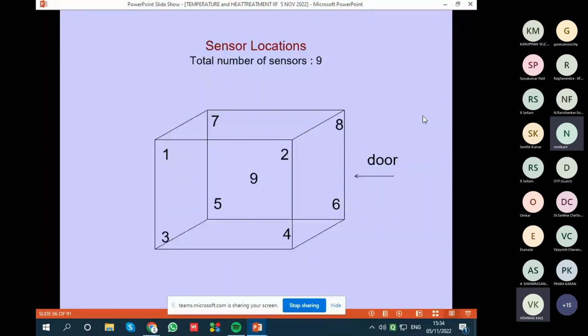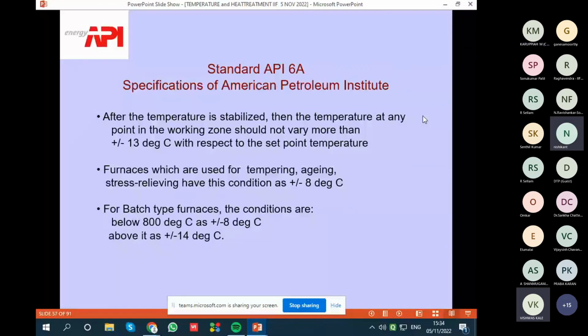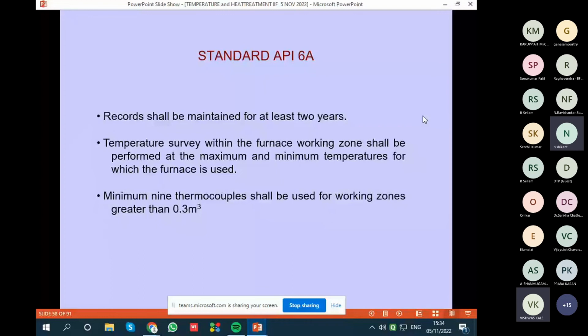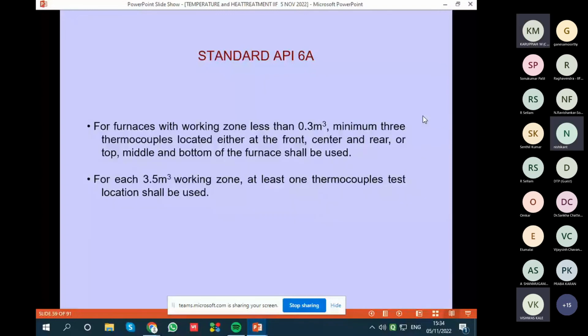Then I'm taking a typical example. The standard set by API 6A says that the variation allowed is not more than 13 degrees, etc. So follow that standard. Then maintain the records. As per the records, there are different numbers of thermocouples, and all the procedure is given there. Follow that procedure, how many thermocouples should be put, etc.